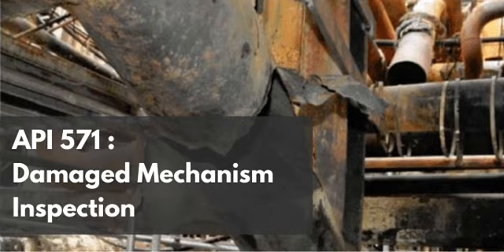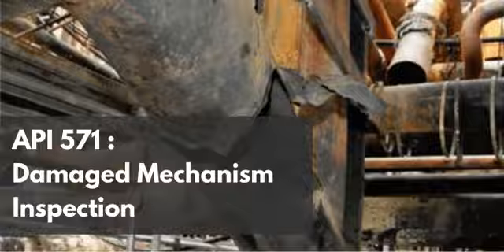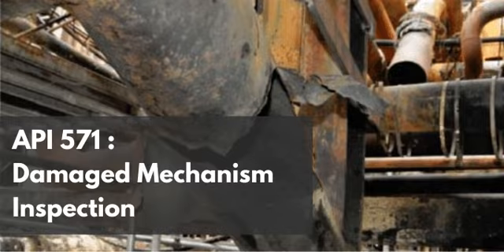When amine equipment is drained for maintenance, it is never truly empty. Right. Microscopic amounts of amine remain trapped in the porous operational scale, or in the microscopic crevices of flanges, or in the rough profile of older welds. So what happens to that trapped residual amine if a maintenance crew skips the extensive water wash and immediately applies a 1175-degree ceramic heating band, or injects 400-degree high-pressure steam to clear the line? You fundamentally alter the kinetics of the cracking mechanism.